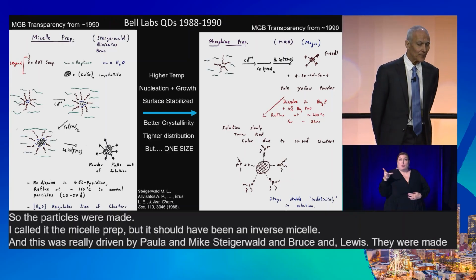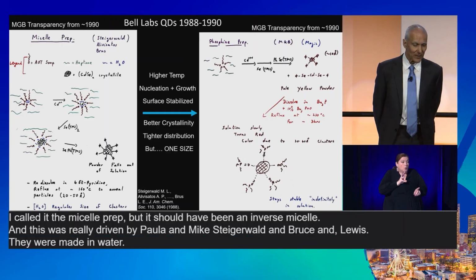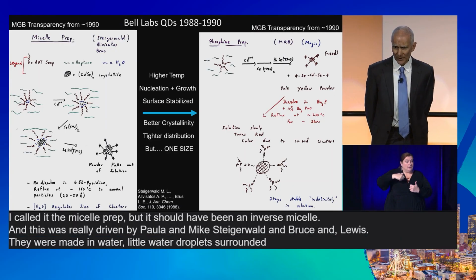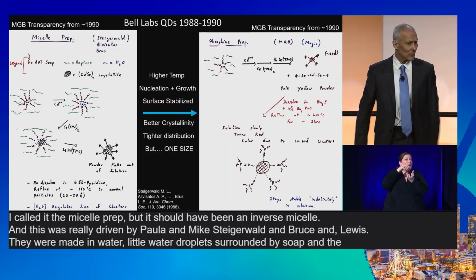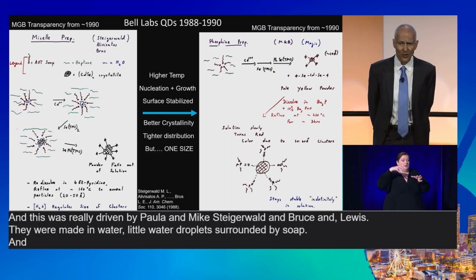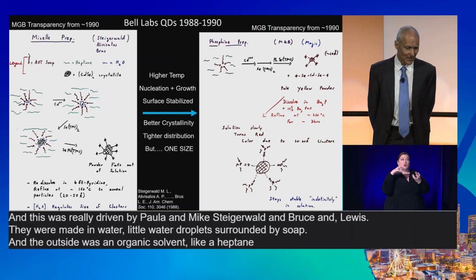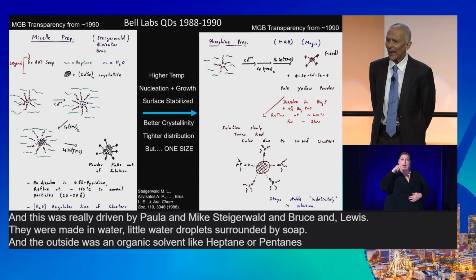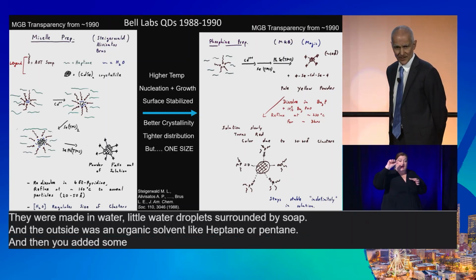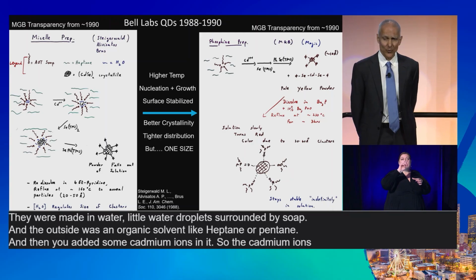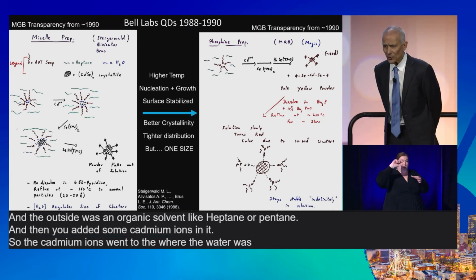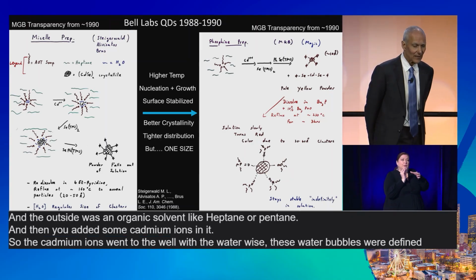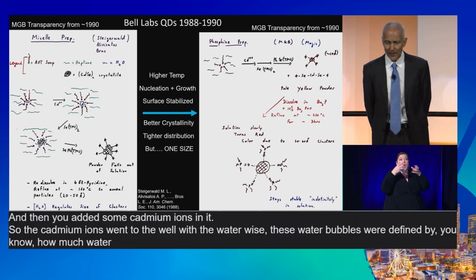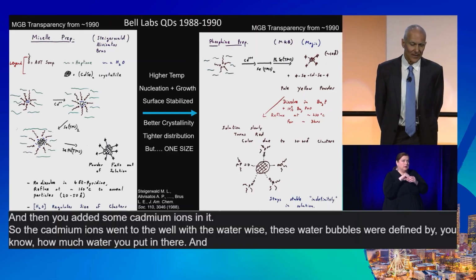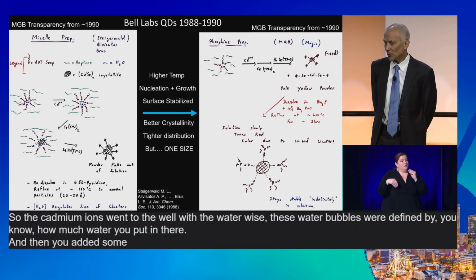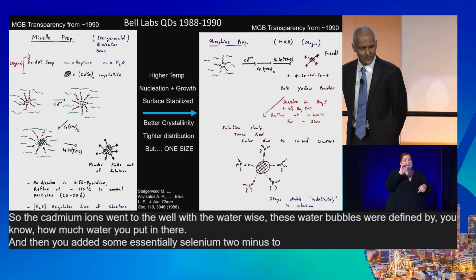They were made in water, little water droplets surrounded by soap, and the outside was an organic solvent like heptane or pentane. And then you added some cadmium ions, and so the cadmium ions went to where the water was. These water bubbles were defined by how much water you put in there. And then you added some, essentially selenium 2-, to make cadmium selenide.